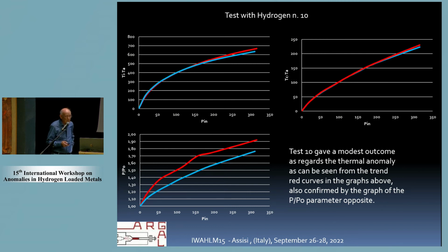And here we have the curves of the test subsequent to test 9. You can see that the powder has been in some way changed, and the extra heat is much less, and also the behavior of the pressure, you can see here, is not quite good. It doesn't decrease too much. So where inside the reactor there is no absorption or strong desorption, the extra heat is not so big.